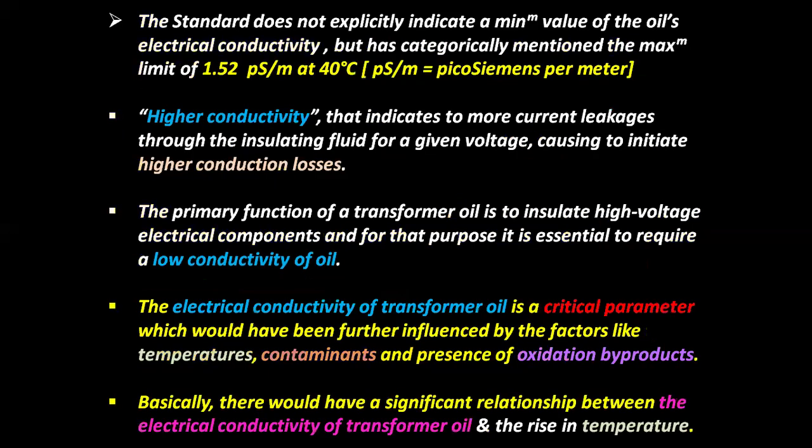The standard does not explicitly indicate a minimum value, but categorically mentions a maximum limit of 1.52 picosiemens per meter at 40 degrees centigrade.